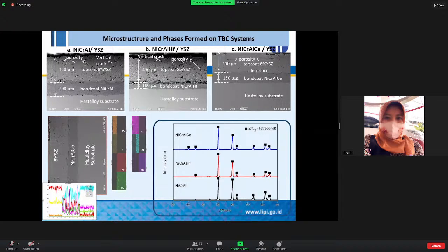The microstructure of the bond coat of nickel chromium aluminum and the other reactive element additions shows that it contains high porosity. Porosity was also observed at the bond coat and top coat interface, like here, which is not favorable due to reducing the strength of the coating system. A TGO was not visible at the interface of all coated samples before the oxidation test.